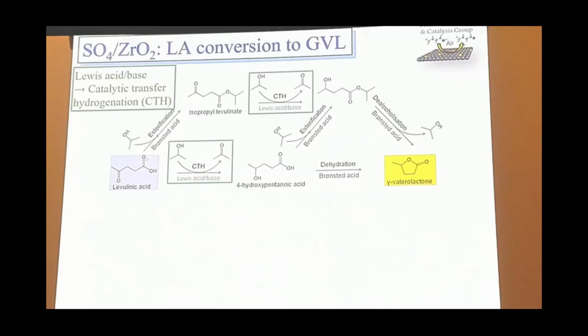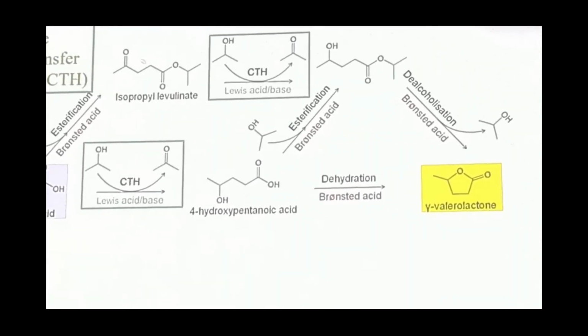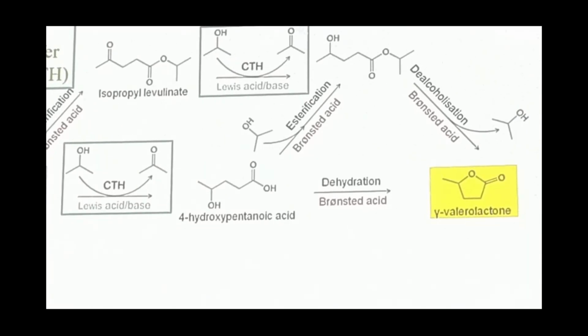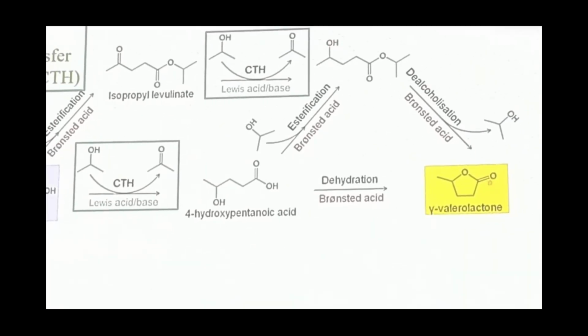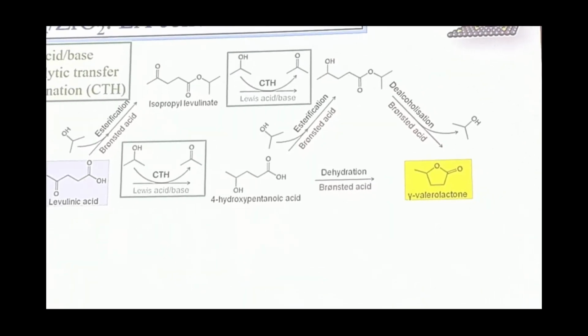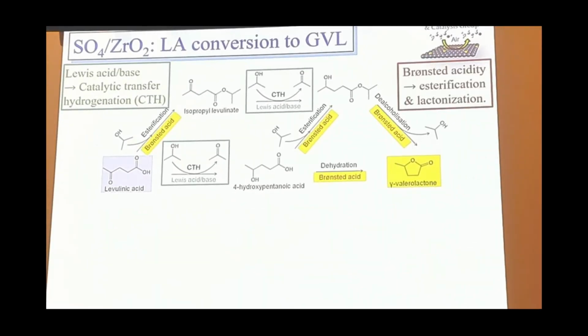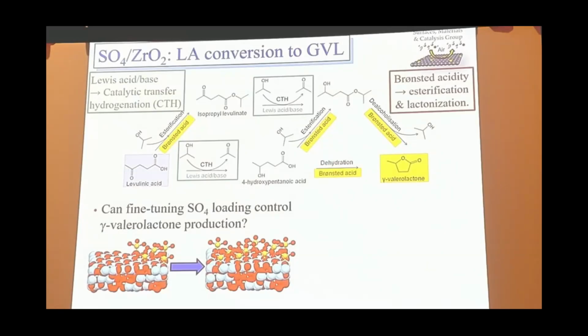If we're reacting with isopropanol, we might have an esterification to form isopropyl levulinate. Then it can undergo catalytic transfer hydrogenation to hydrogenate the ketone group, and then it can cyclize and decompose through to the lactone. But what we can see in each of these steps is we either have steps identified as proton catalyzed, or it's Lewis acid catalyzed, which is the transfer hydrogenation step. So again, thinking about how we can tune the properties of the zirconia, and we talked about with the glucose isomerization, you would expect to have a partially sulfated surface, sulfated zirconia.